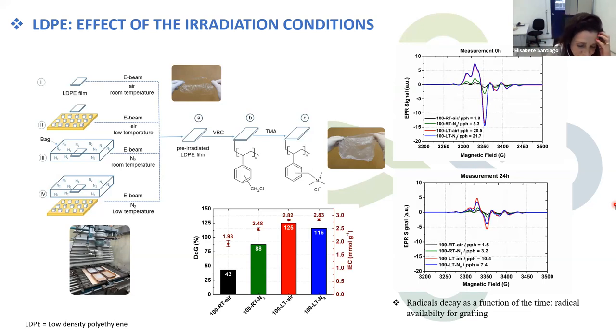Polyethylene is very interesting because it's a non-perforated membrane. So you can promote a very large number of radicals that can be used for grafting and for crosslinking. So that's very interesting. So in some LDPE radiated at different conditions, you have observed that IEC follows the same trend that you observed for DOG. I mean, you have some grafting here, and the grafting is completely dependent on the temperature and the atmosphere. More the temperature than the...